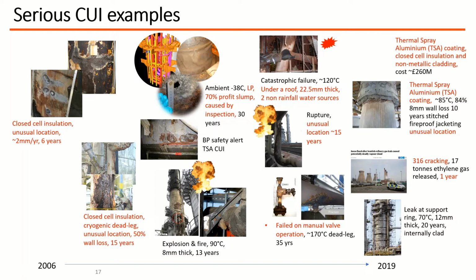Sometimes we think that stainless steel fine cracking or pits, tiny pits, have lower release rates compared with carbon steel failures. But in 2017, this UK failure released 17 tons of ethylene gas very quickly. It actually occurred after only 1 year in service, and that's another issue really, is that periodic inspection is not really going to be effective at preventing the first stainless steel failure. So really the best control we have to prevent stainless steel failures, or the first failure from being a surprise, is, well, to coat it and then periodically reinstate the coating. And this is why water monitoring is particularly interesting in the future for stainless steel systems, because inspection isn't really very effective.